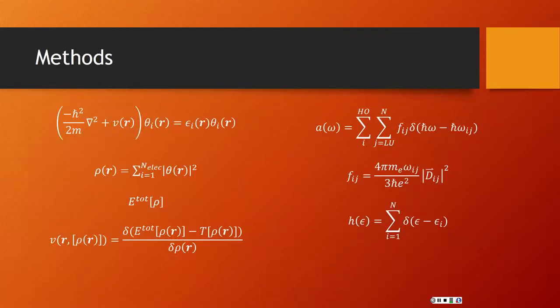So if you look here, the absorption spectra depends not only on whether or not a transition is allowed, that is, whether there's an open state for it to jump to, but also on the oscillator strength. And since you don't have any introduction of the Coulomb interaction between your electron and hole, the energy of this jump from electron to hole state would be just the energy of your occupied ground state orbitals minus the energy of the unoccupied orbitals. So then it should completely correlate to your band gap, but it doesn't.